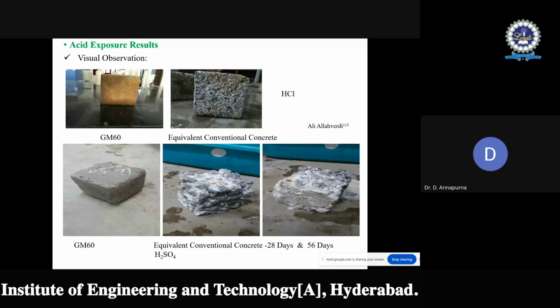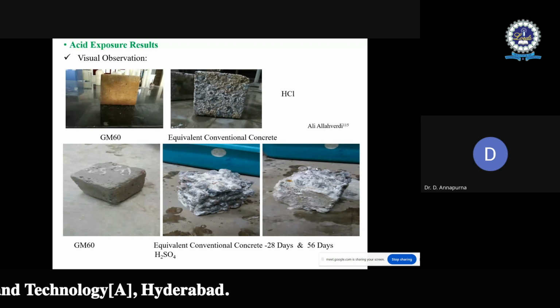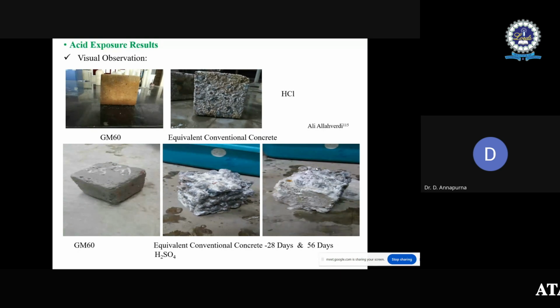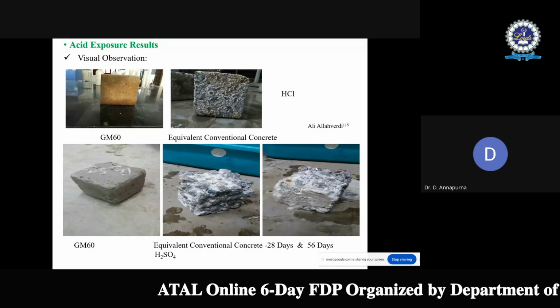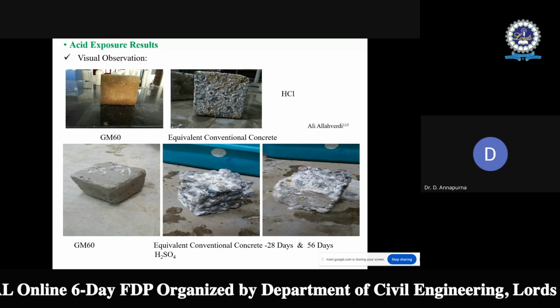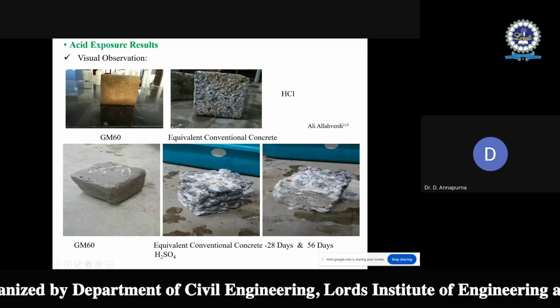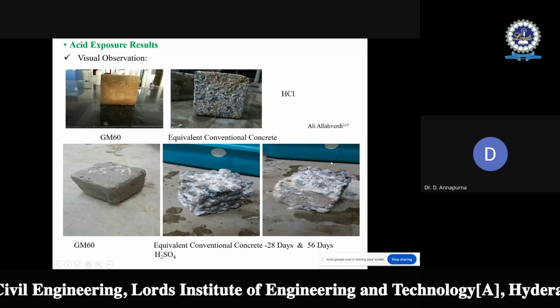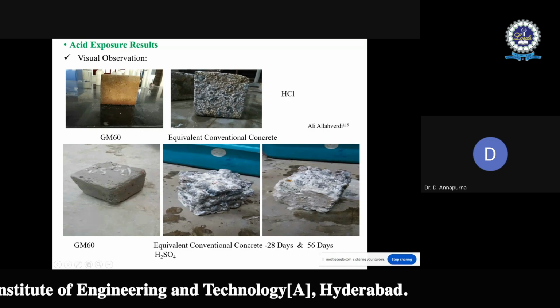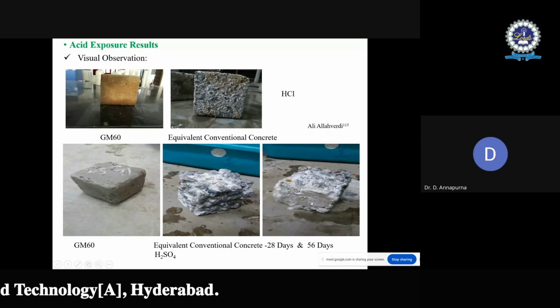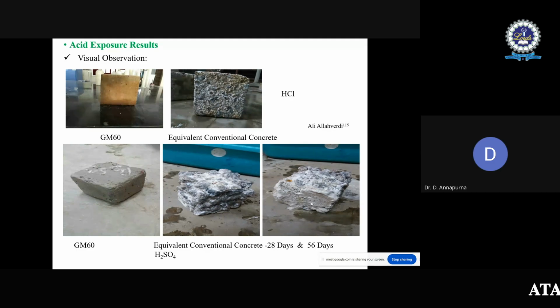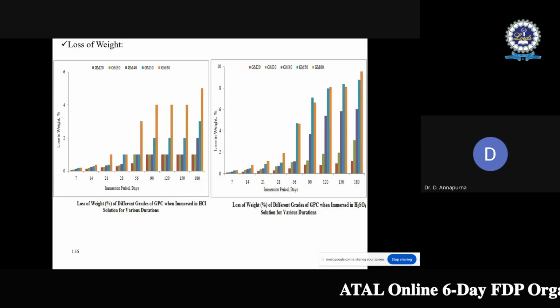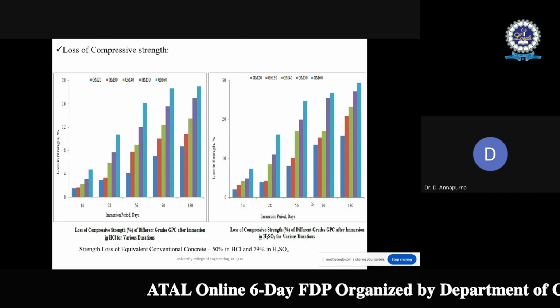So with this we can clearly say that the proposed grades of geopolymer concrete are showing a high, superior resistance against sulfuric acid compared with the conventional concrete. Because after 180 days also aggregate exposure is not seen, but the conventional concrete specimens were taken out from the solution after 56 days only. So it ceased after 56 days only. The same is confirmed through loss in weight and loss in compressive strength.